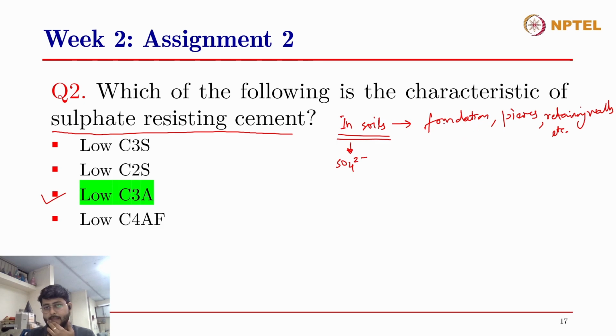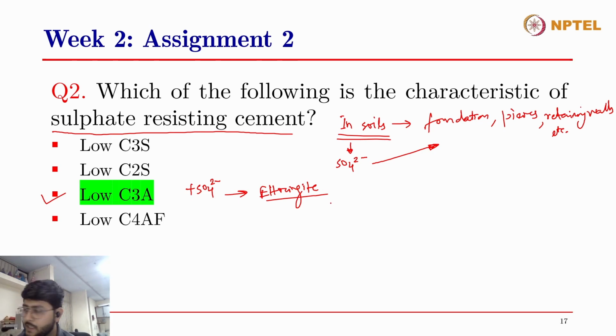Now, it is fine when we also add sulfate to the cement in the form of gypsum to control the setting of cement, right? So when sulfate is available in the cementitious system at an early stage, when the cement or the concrete is plastic in nature, the C3A can react with the sulfate. The aluminates react with the sulfate and water in order to produce ettringite. Ettringite is good for us when the cement and concrete is in its early age, meaning that it is in a fresh or flowy state.